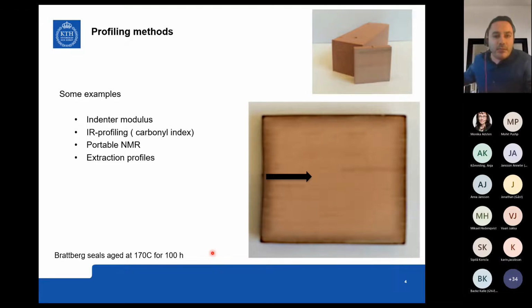The image you see here on the right is a cross section of one of these cable transit seals. I just wanted to show this image because when you do a high temperature aging, you get this non-homogeneous oxidation. You get a lot more oxidation at the surface compared to the bulk. So when you do these accelerated aging tests, you need mechanisms and tools where you can understand what's actually happening in your material and assess what is actually mimicking the reality mostly.